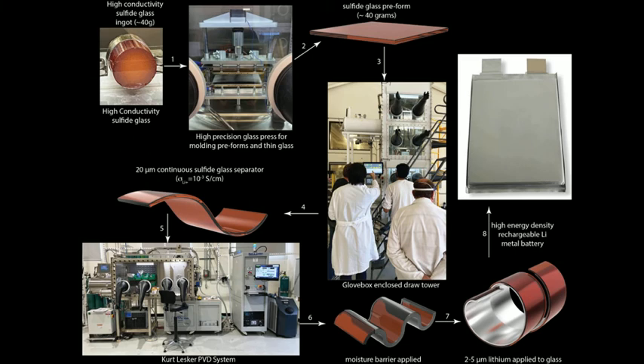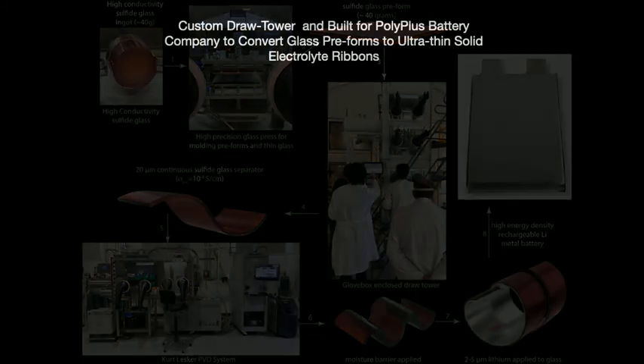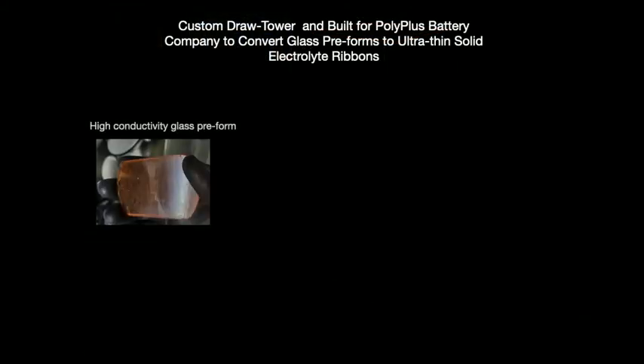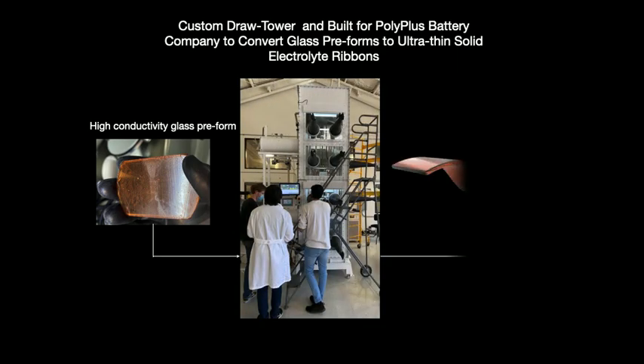The process for making thin glass looks something like this. You start with an ingot of glass that is then pressed out into a preform. The preform goes into a draw tower. Draw towers are known in fiber optics; that's how you draw an optical fiber. And then we have a Kurt Lesker system for depositing lithium. And ultimately, we will move toward building pouch cells. So inside that draw tower, basically, we start with a preform, a block of high conductivity sulfide glass. It goes through that draw tower. It comes out the other side as thin glass.